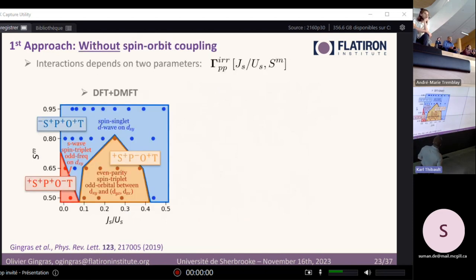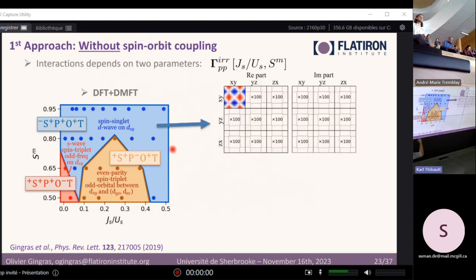So now I'm going to show the leading eigenvalue and the symmetry of the leading eigenvector, depending on, here, a phase diagram. So it depends on the interaction that we use to model the on-site particle-hole vertex. So basically, we choose an interaction, we do the whole framework, and we find one leading eigenvector. We look at its symmetry, and here it is. So in the blue region here, this state is purely spin singlet,